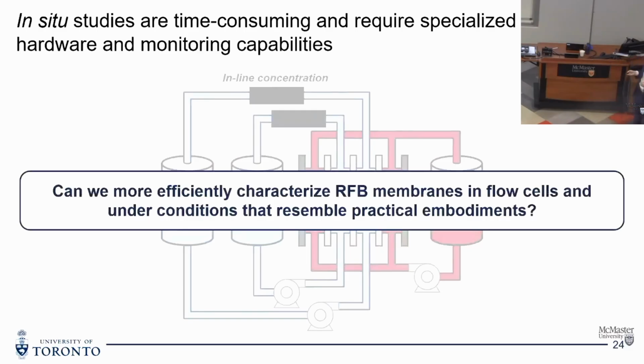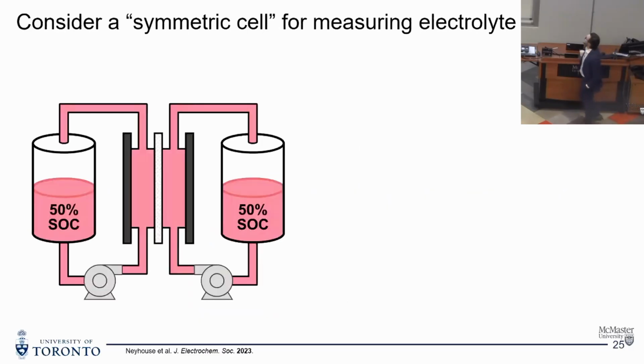And so what we wanted to ask is if we could more efficiently characterize membranes in cells and under conditions that more reflect the type of system we're encountering. So what we did is we turned to something we call a symmetric cell. This is better put as a do-nothing cell, where this is a way we typically characterize stability of our active species, where we cycle the material against itself.